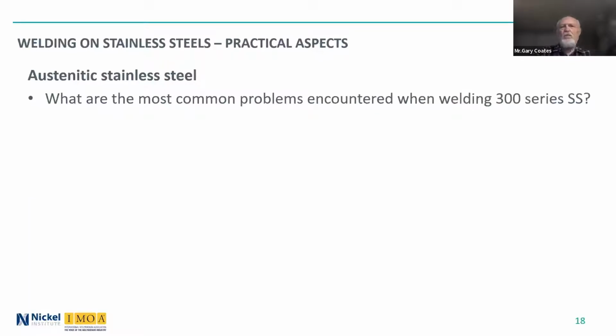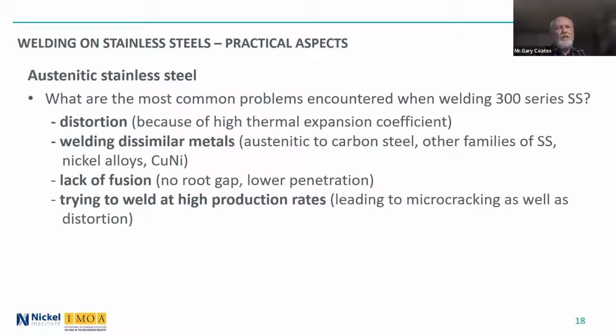So what are the most common problems encountered when welding 300 series stainless steels? Well, the first one, just taking from my experience, is distortion. The 300 series have a high thermal expansion coefficient compared to carbon steel and the other families of stainless steel. And so distortion is really the number one concern that we have, in my experience. And it's also very difficult to combat.